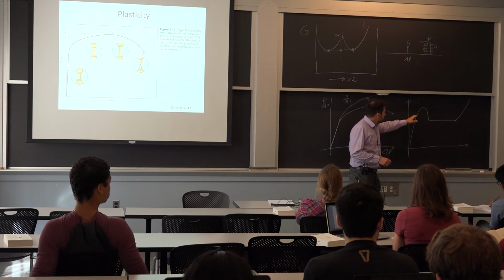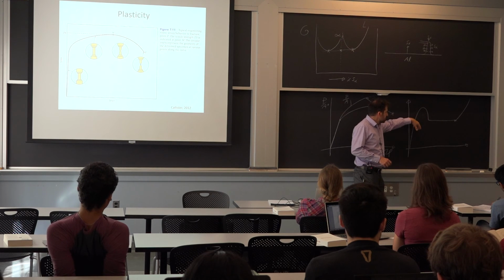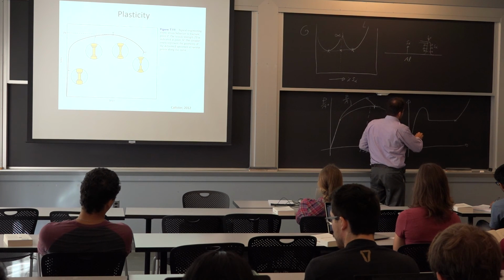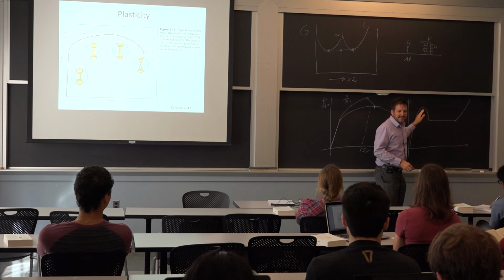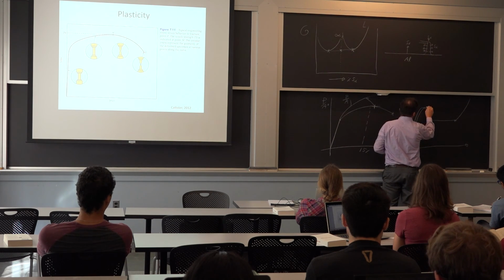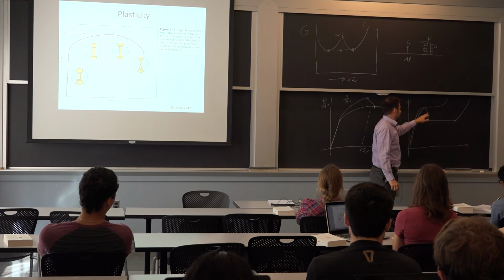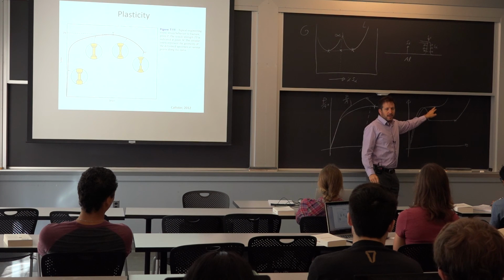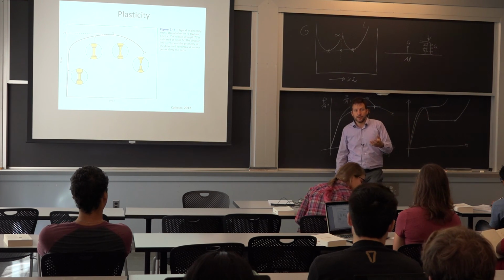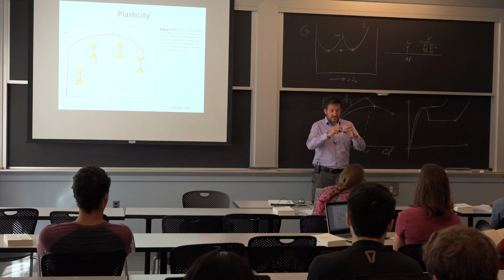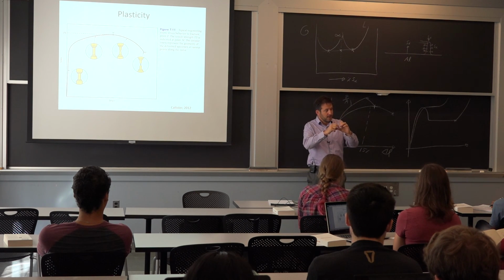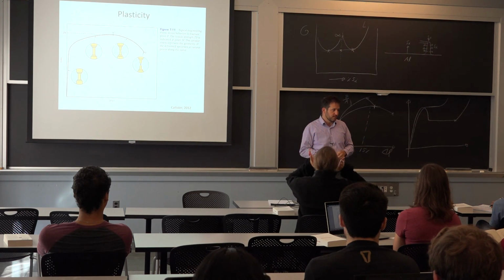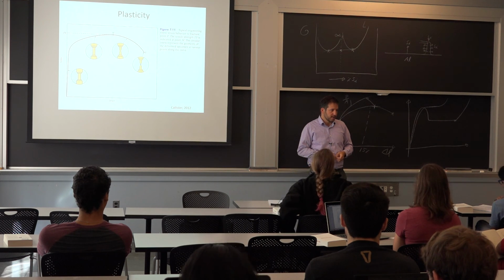If you are to plot this behavior of the polymer on a true stress through strain, it kind of levels down. It will be something like this, and it will have more hardening later. I think it's always positive, but it's very low, and that's why the neck is so pronounced. You're looking here. If you start with the sample, you see it's going to thin down by a factor of half in one area, and then that region stretches, and you end up with 600% strain in your thermoplastic. So it's just what happens.